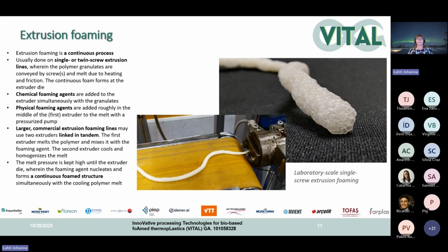This is a pictures and explanation about extrusion foaming. I don't think I have time to go all the details of the different technologies, but you can later on check through the descriptions of different technologies. But basically, extrusion foaming is a continuous process, and we can use different type of extruders there. We can use single screw extruders, or we can use twin screw extruders. And as explained before, we feed the polymer granulates inside the extruder, and then the screws convey the granulates and melt the granulates with the help of heat and friction, and then we create the foam as explained during the previous slide. And in extrusion foaming, we can use both chemical foaming agents or physical foaming agents.